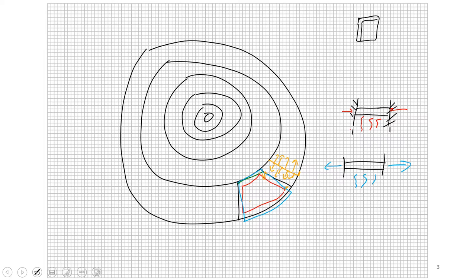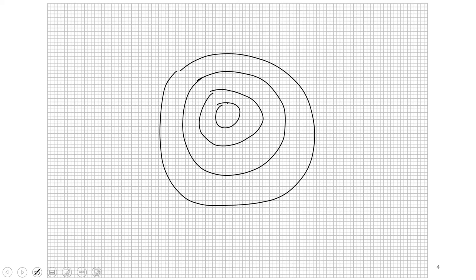So in reality, if I were to draw what a tree trunk actually looks like under a rapid high temperature drying stress condition, what you end up with is something like this. This uneven drying process ends up forming radial cracks in the log, cracks that are perpendicular to the growth rings of the tree, going into the trunk of the tree and running parallel to grain. So these cracks will run both perpendicular to the growth rings and parallel to the wood grain, and we refer to these as checks.